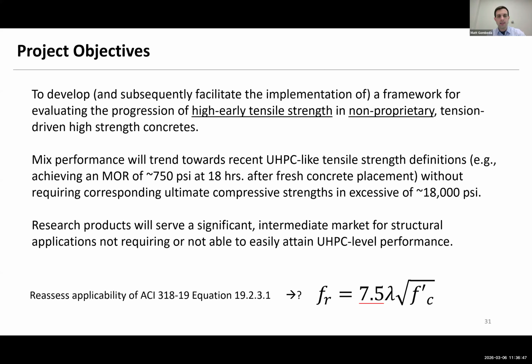And typically you can hit that number with UHPC or really high strength concretes, but we wanted to create it in a mix that would not have the difficulties or the added complexities of UHPC and also wouldn't tie it to a compressive strength of about 18,000 psi or so. So it was really performance specifically targeting that flexural strength. Again, great for the precast industry, also great for things like tall building construction where they need to keep moving up floors and release shoring and that sort of thing.